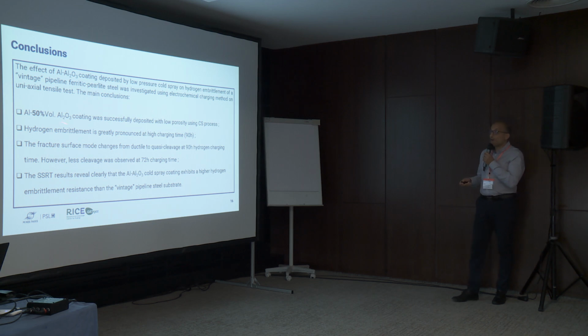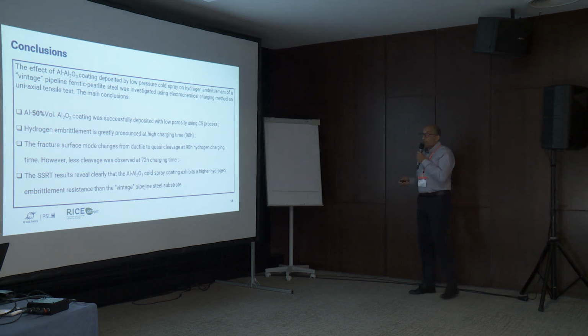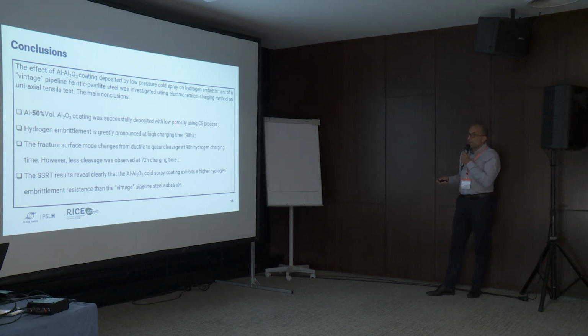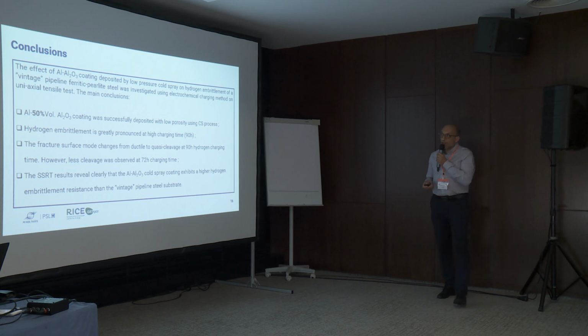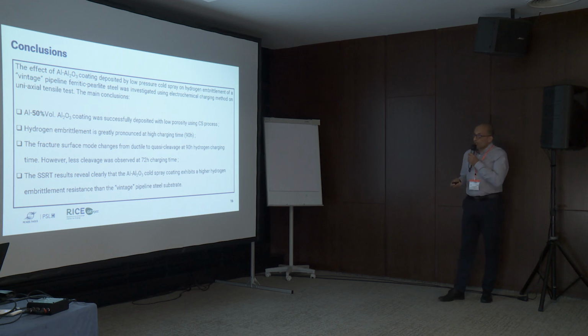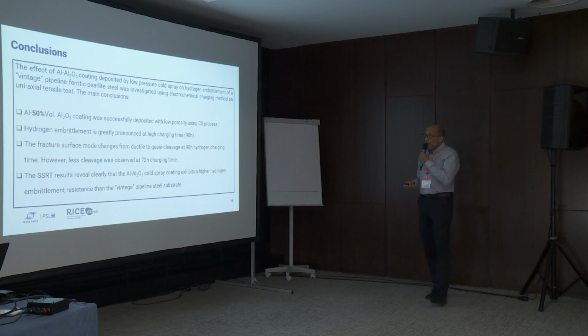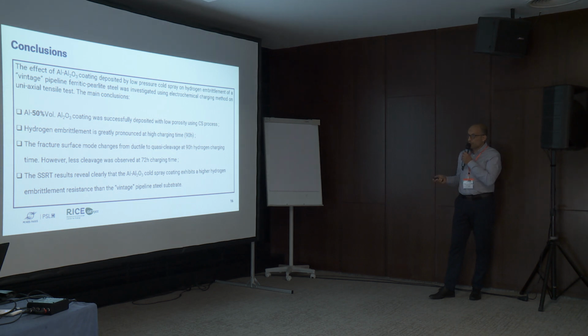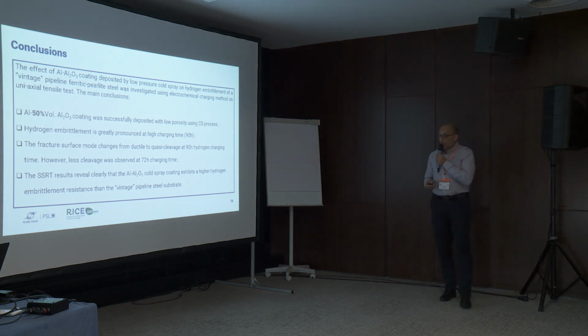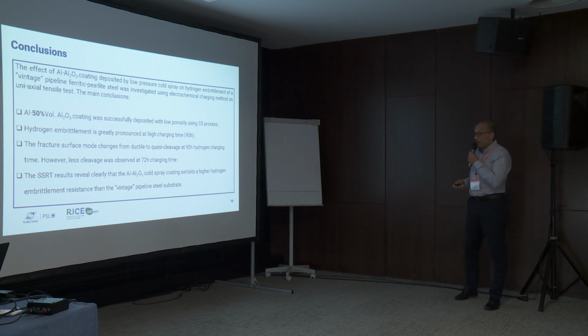So to conclude, we have a composite aluminum and alumina coating, which has been successfully deposited with low porosity using this cold spray process. Hydrogen embrittlement is greatly pronounced at high charging condition. The fracture surface mode changes from ductile to cleavage at 90 hours hydrogen charging time. However, less cleavage was observed at shorter charging time.